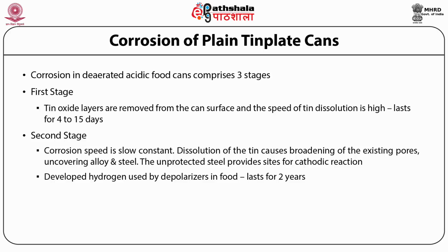Once the internal pressure in the can causes the ends of the can to bulge, which is sometimes thought of as microbial spoilage, but actually it is due to the production of hydrogen. The bulge causes the product to be no longer sellable, as a swollen can is normally thought of as microbial spoilage and not hydrogen evolution.